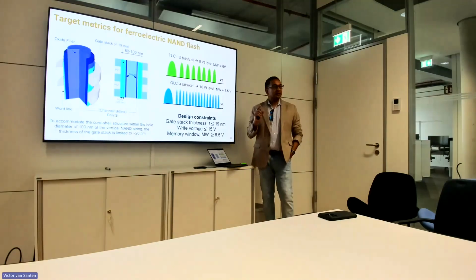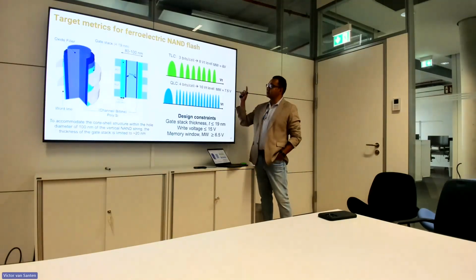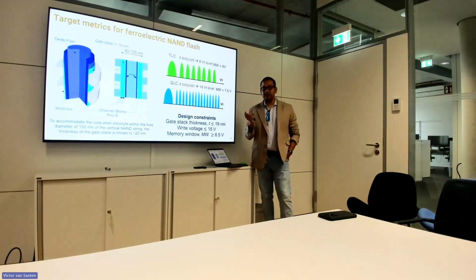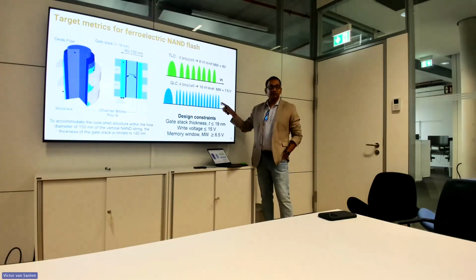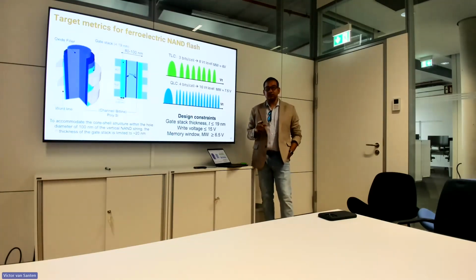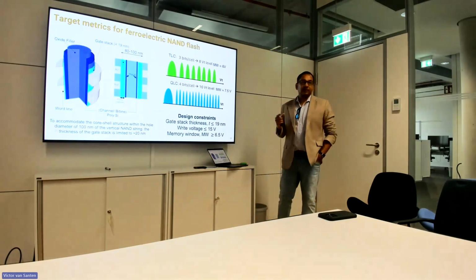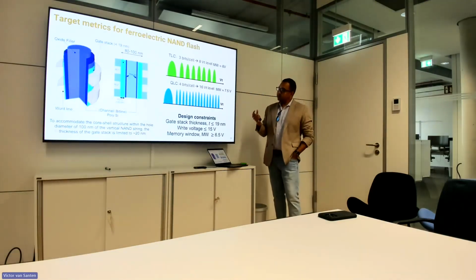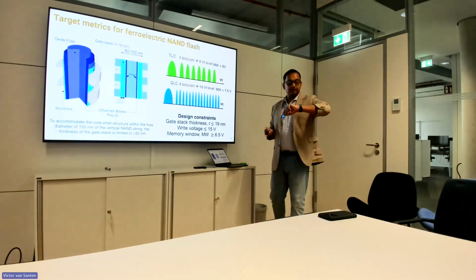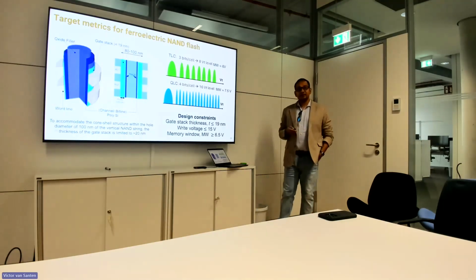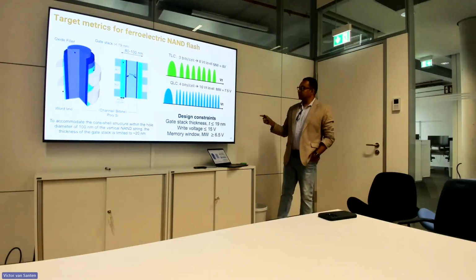But another thing that I also hear is that SLC, TLC, QLC, all are actually the same chip. So basically the QLC chip, you also can use it in SLC mode. But in doing so, you cannot actually reduce the voltage significantly lower than 20 volts because the stack design is the same. So irrespective of whether using SLC or QLC, your write voltage will remain almost the same. Okay. The latency will be the same. Okay, but nonetheless, these are the parameters that we have.